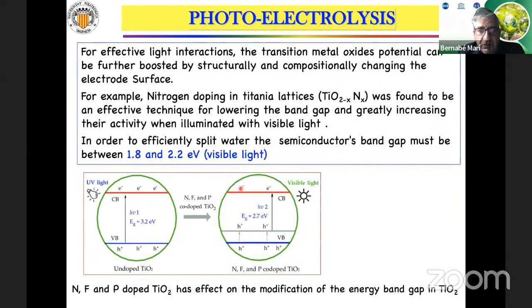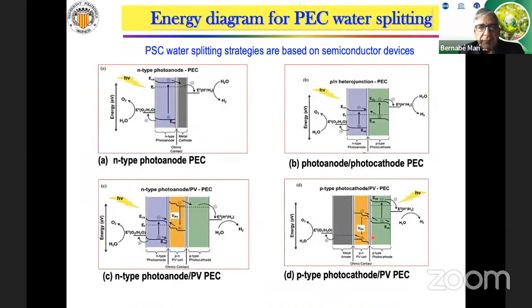Well, another way to reduce the band gap of titanium oxide is to dope with nitrogen, fluorine, or phosphorus, just to decrease the band gap and be able to absorb more photons. Well, photoelectrochemical water splitting is based basically on semiconductors. So there are several possibilities. We can use mainly N-type photoanodes, or photocathodes, or P-types, but everywhere are semiconductors. So the photoelectrochemical water splitting strategies are always based on semiconductor materials, semiconductor devices.